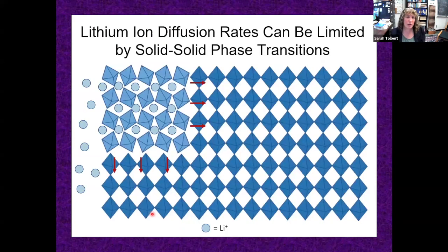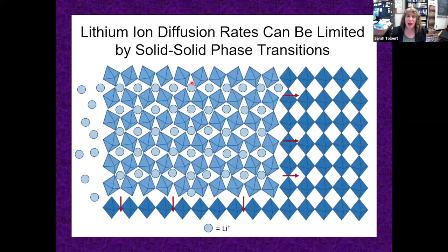So let me show you a picture that better illustrates that. Let's say this is our crystal structure without lithium, and this is our crystal structure with lithium. The lithium is small and can move easily, but the heavy atoms are much harder to move. And in order for this lithium to move, the entire phase front has to propagate through the material. What's even worse is this lithium needs to come out here, but the new lithium needs to go in here. And when it tries to move through this domain, every lithium site is full. So there's no easy way for the lithium to move through this domain.